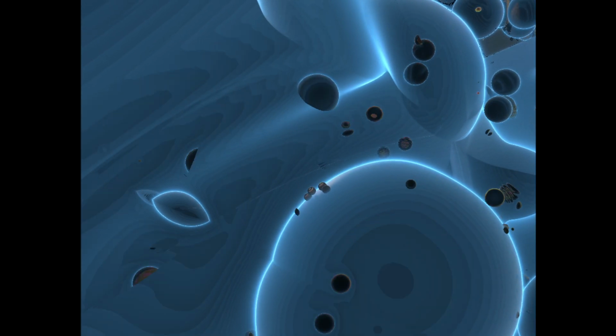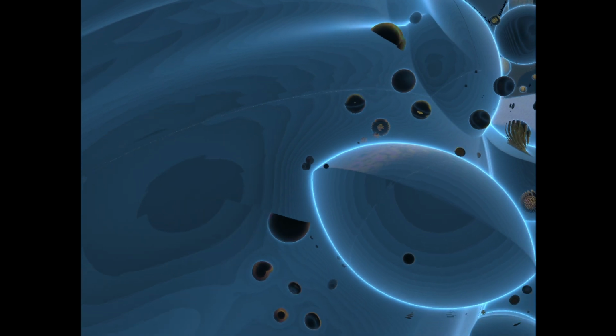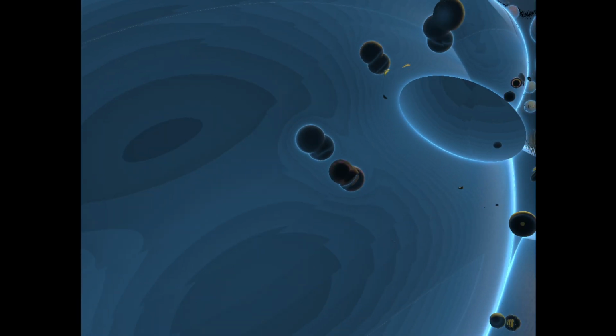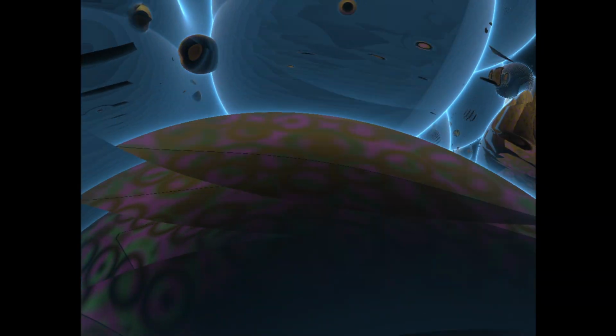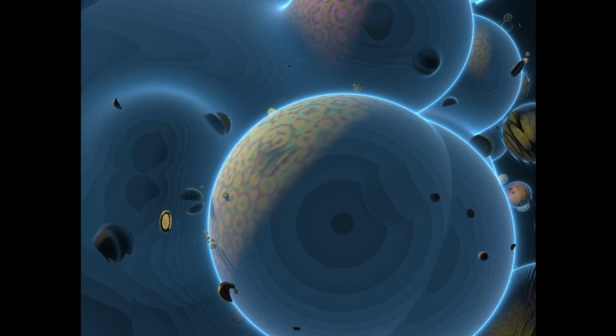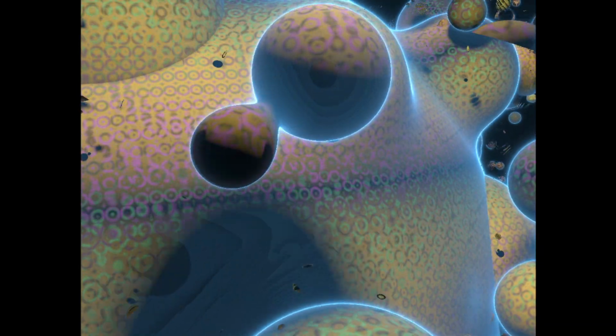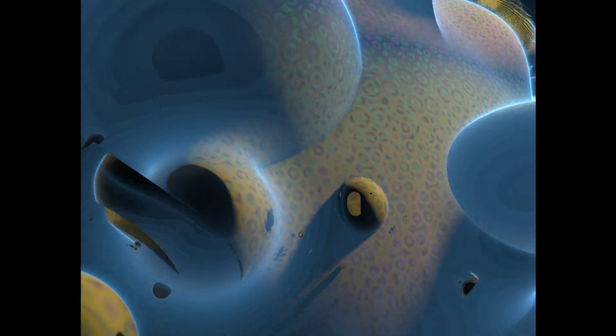Okay, so less stuck. And that leads us to the really big difference. The absolute core concept for FeSCs, they are intrinsically multi-orbital systems. Right. Explain that a bit more. So in cuprates, you can often boil down the essential physics to electrons in basically one specific orbital, the dx2-y2 orbital on the copper atoms. A single player, effectively. Pretty much. But in FeSCs, the action involves electrons in at least three different 3d orbitals of the iron atom, typically the dxz, dyz, and dxy orbitals. So it's like a team effort within each iron atom. Exactly. And these different orbital flavors of electrons are all active near the energy level where conduction happens, the Fermi level. They hybridize, they interact. It makes the electronic structure vastly more complex.